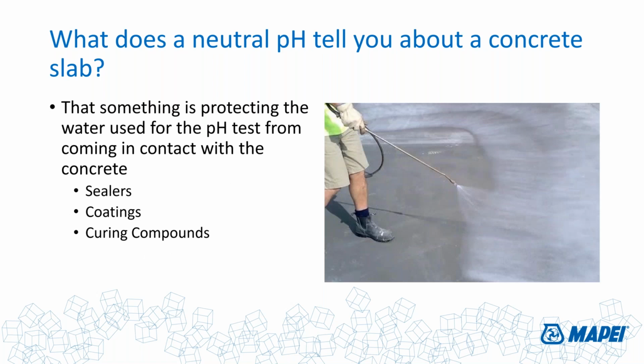What does a neutral pH tell you about a concrete slab? If you put your drops of water on a concrete slab and I'm still getting 7, which is neutral water, it tells you that there's something on the slab that's inhibiting the water from actually coming in contact with the concrete itself. Things like sealers or coatings or curing compounds are something that you might not necessarily see. They're clear, generally speaking, but they're prohibiting that water from